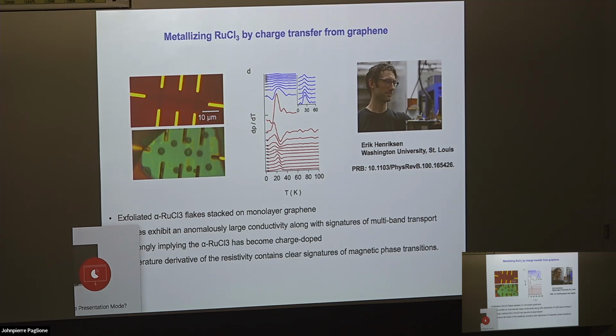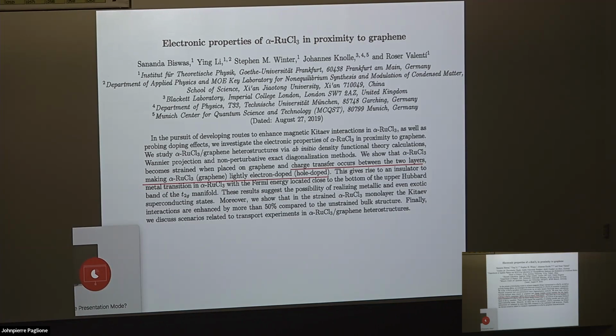And so what Eric actually discovered was that when you put graphite or graphene on top of ruthenium trichloride, you had charge transfer. You actually metallize the ruthenium trichloride. This became even more clear after Roser Valentí's group studied this problem theoretically. Charge transfer occurs between the two layers, making the ruthenium trichloride electron doped and the graphene hole doped. That's pretty well understood. So that's a very interesting way of metallizing a Mott Hubbard insulator, by putting it in contact with something. So that was kind of new too.